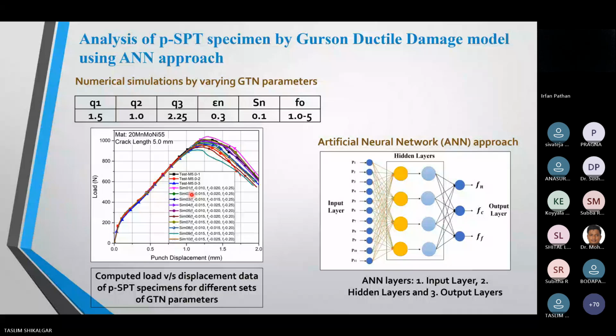FN is the void volume fraction at nucleation. The second one is the void volume fraction at coalescence, and the third one is the void volume fraction at final failure. So I varied these numbers, performed multiple simulations, and compared this load displacement data with the experimental data. I observed that my data falls between the upper and lower bound of this numerical data.